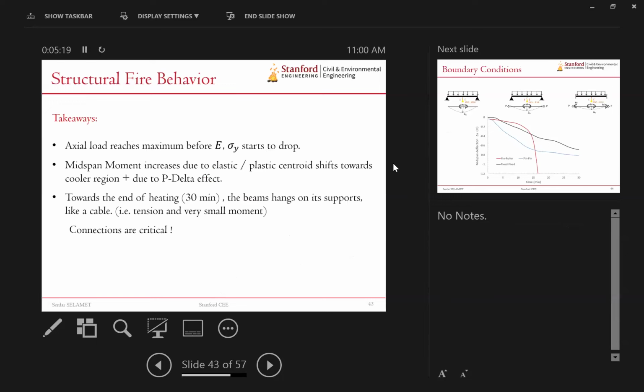The takeaways from this: axial load reaches maximum before Young's modulus or yield stress starts to drop. So axial load is a geometrical problem in the beginning, how things actually deflect vertically, rather than a mechanical problem. The second one is the midspan moment increases due to elastic or plastic centroid shifts towards the cooler region, plus the P delta effect. Those two things act together to add additional moment to the midspan, which is the worst case. Towards the end of the heating, the beam hangs on its supports like a cable. Tension is there, and also a very small moment, so no bending. And here the connections become quite critical to design.